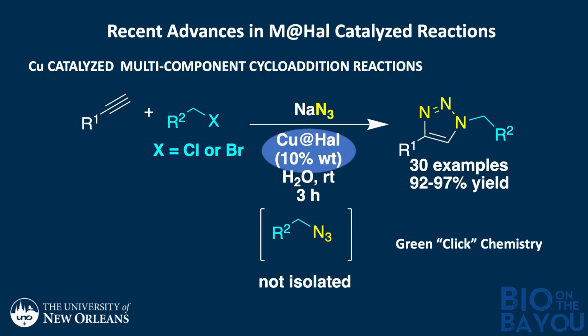Now, we've since developed this chemistry for a copper system. In the copper system, we applied it to the multi-component cycloaddition reactions for the synthesis of triazoles, or green click chemistry. The advantage of this system, again, is we can do this reaction completely in water, but we also don't have to isolate this treacherous alkyl azide. Basically, we can go from a starting material to product cleanly and in high yield. Again, we made a triazole that